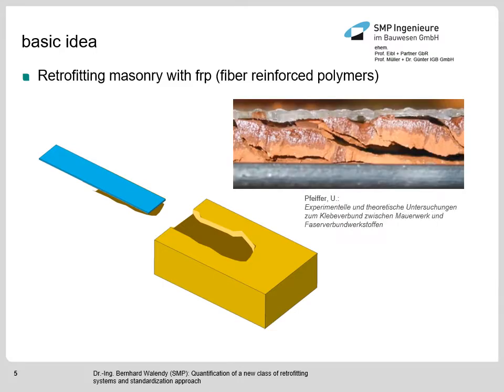And here is a photo shown from the PhD thesis of Uwe Pfeiffer from Kassel. And this cohesive failure is shown again. As you can see here, there's a fiber reinforced polymer glued on a masonry stone, and a very thin layer of masonry stone, let's say something about 1 centimeter thick, is cracked and separates from the masonry stone. This is the standard failure mode for fiber reinforced polymers if you use standard glue, which is in most cases very stiff epoxy glue.